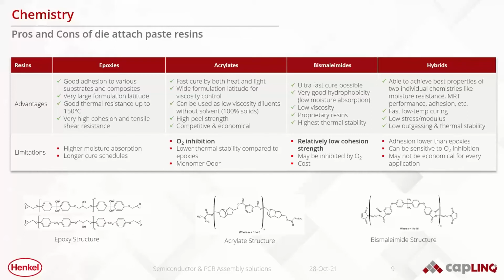The base chemistry of the material that's used is also very important, and the materials that we have cover a wide range of base chemistries. Epoxies have been used traditionally and historically because they have a very good adhesion to a wide amount of substrates, and also because they have very good thermal resistance up to 150 degrees Celsius, and in some cases higher. But other chemistries exist. I won't talk about silicones right now, but I will later on.